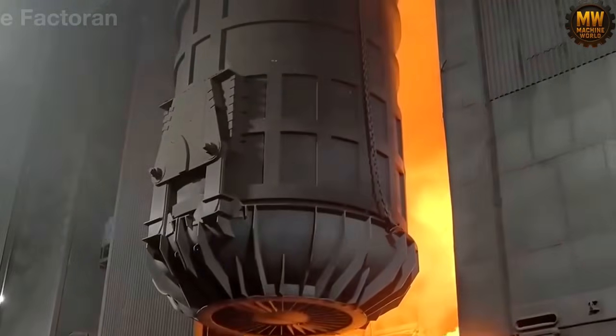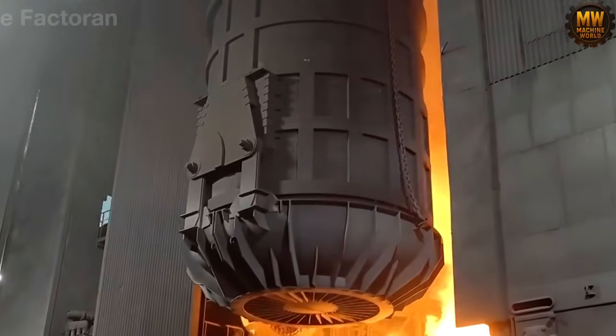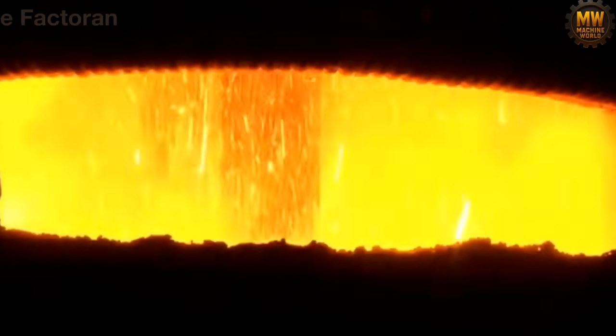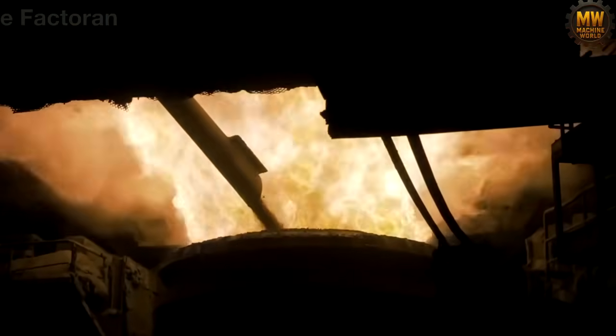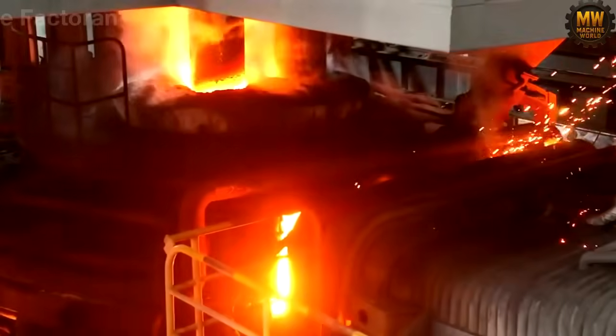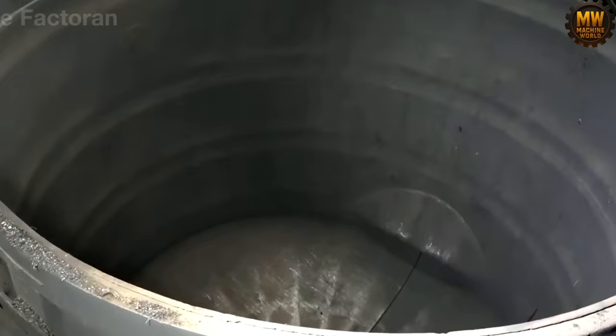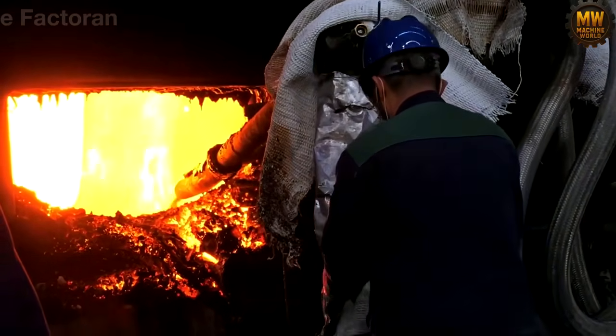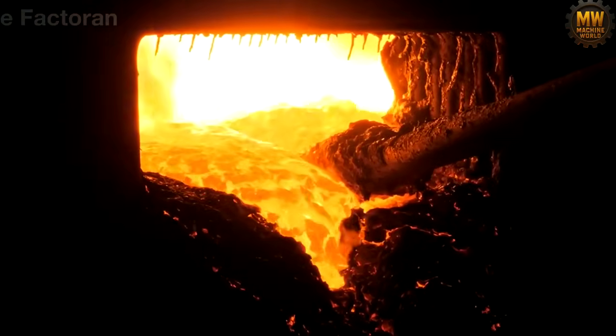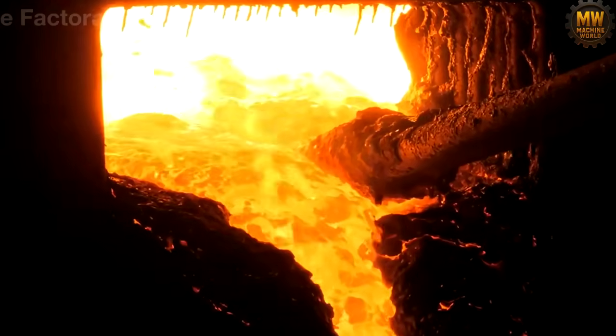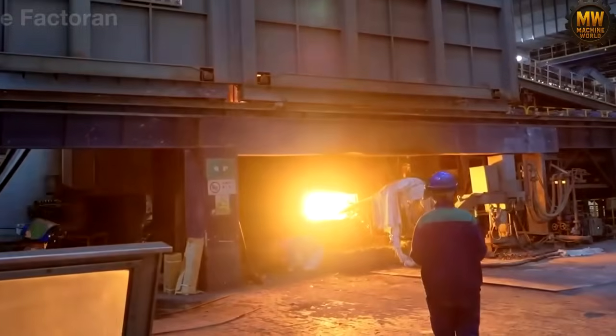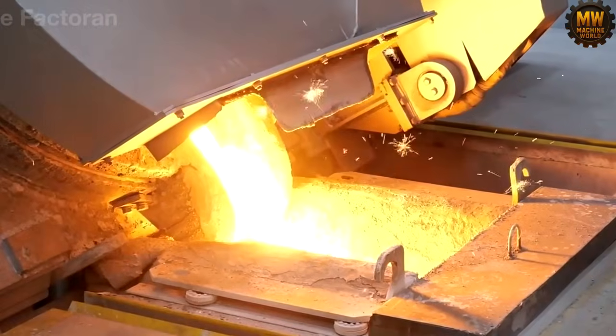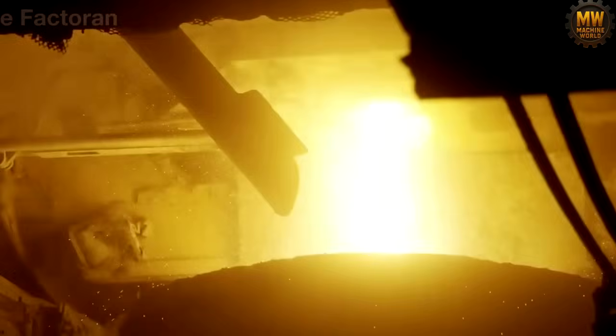But melting is merely the brute force phase. Next comes the chemical purge. Lime and engineered fluxing agents are blasted directly into the liquid pool. They hunt down non-metallic impurities. These agents aggressively bind with unwanted elements, dragging them away from the valuable steel base. This toxic chemical cocktail rapidly rises to the surface. It forms a thick, glowing crust of slag. Heavy automated rakes physically scrape this contaminated foam away from the pristine liquid beneath.